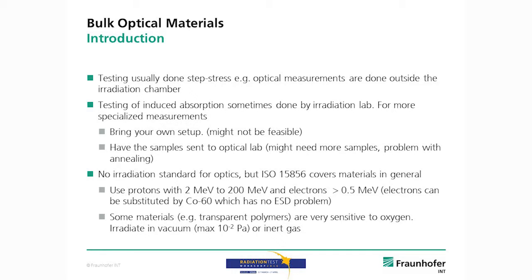To my knowledge, there's no dedicated standard for irradiating optics. There's an ISO standard, which is also referenced by the ECSS. That's ISO 15856 about material irradiation. And this usually asks you to use protons of 2 MeV to 200 MeV, if you want to test for protons, and electrons larger than 0.5 MeV. And the electrons can be substituted by cobalt-60, which has the advantage that